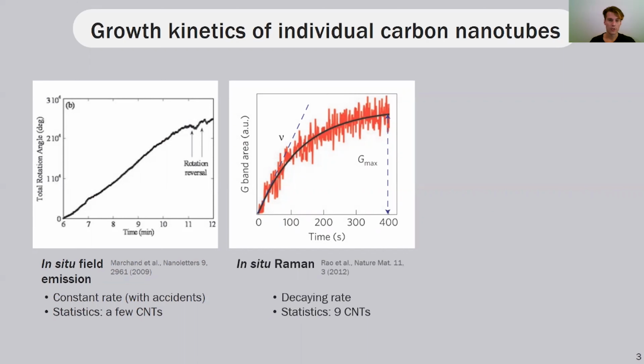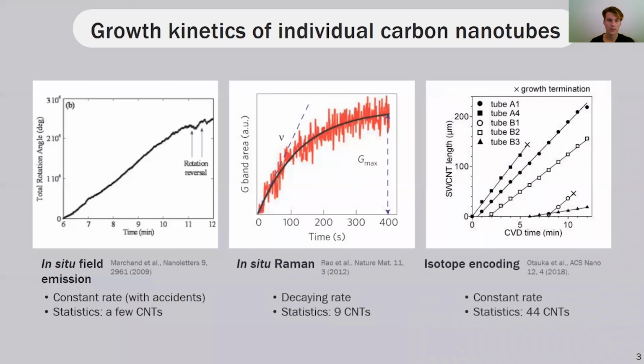This method allowed measuring nanotube kinetics, which can be described by an auto-decaying process, which can be the evidence of catalyst deactivation. One of the most recent methods was developed by a group of Shigeo Maruyama. They put isotope labels on the nanotubes during their growth, by diluting ethanol, which was used as a carbon precursor, with ethanol containing isotope carbon-13 at particular moments of time. And after synthesis, they determined the position of these labels using Raman. And the distance between these positions allowed them to access nanotube growth kinetics.